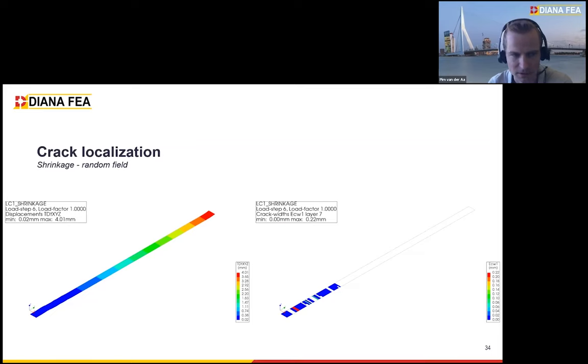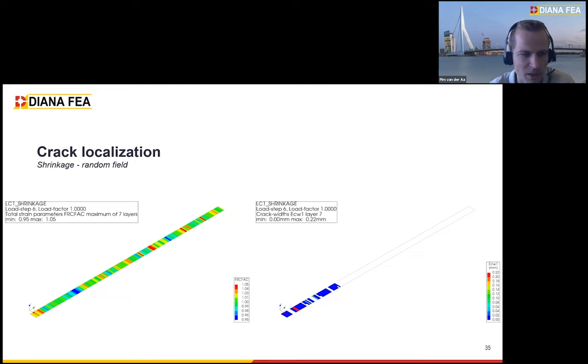In the next slides, we are going to apply the random field. You can see that the shortening is now 4 compared to the 4.3 in the previous slides, and you can see that there are localized cracks occurring. If you add the sizes of those cracks, you come to something like 0.3, which was the difference in displacement. That is because the random field is applied over this slab, over the entire stress-strain relationship of the tensile side. It's from 0.95 up to 1.05, so maximum 5% difference. By taking this into account, you get a much more realistic crack pattern than if you do not take it into account.